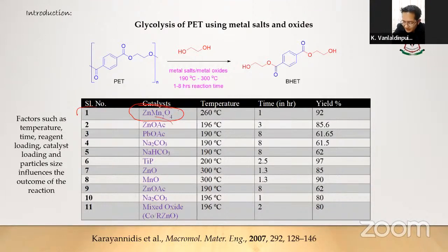But if you use zinc acetate at 196 degrees Celsius, the reaction is completed within 3 hours, giving almost 86% yield. But when you use that same catalyst, zinc acetate, entry number 9, okay, if the reaction is carried out at 190 degrees Celsius, the reaction takes 8 hours to complete, and it gives only 62% yield. So there is a huge difference when you decrease the reaction temperature by just 6 degrees Celsius.